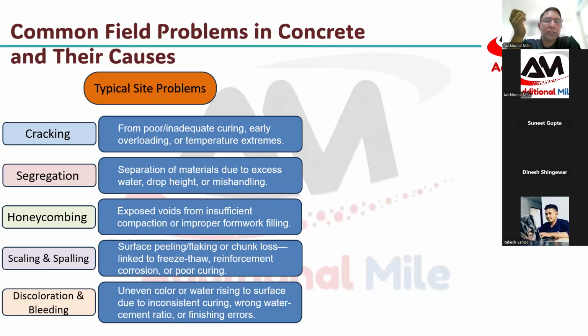segregation, where the material separates due to excess water maybe, sometimes a very high height drop, or mishandling, in the sense someone has added water, someone has applied excess vibration. Sometimes I could see that people do heavy vibration in slab work also. Come on, a slab is hardly 150 to 200 or 250 thick. You don't need heavy vibration there. But still people do heavy vibration just to ensure a factor of safety. So we should refrain from such things. The more you vibrate, the aggregate will settle down and slurry will wash away. That is also a part of segregation.